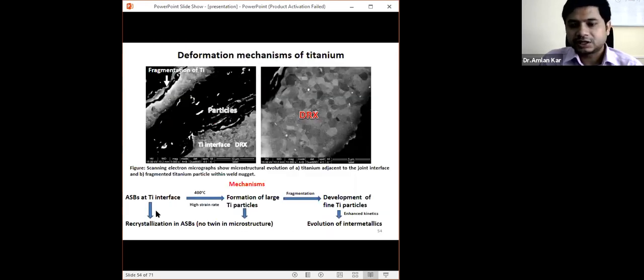And at the interface, we can see a completely recrystallized microstructure, and because of that there is fragmentation also in the particle. You can see this particle is fragmented from this particle. This is the original particle. From here the particles are being fragmented, and subjected to further fragmentation, and that leads to the formation of very, very fine particles. So the mechanism we have developed is that the adiabatic shear band is the only mechanism through which we can explain this phenomenon. There is a formation of adiabatic shear band, and it is noted that in the adiabatic shear band the temperature is very, very high.